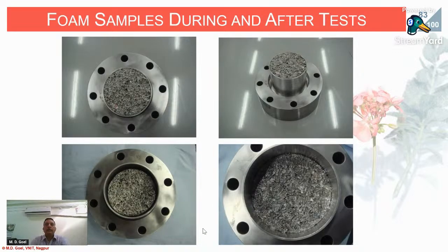So this is the situation of samples before and after the test. We did this test in the shock tube, the samples were placed, it was fired, and loading was applied. Here you can see how the samples were completely crushed. Once this is crushed, it will also get reflected back to the shock tube, and we have pressure sensors or gauges located at different locations.